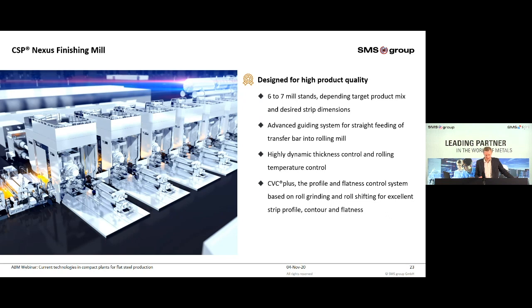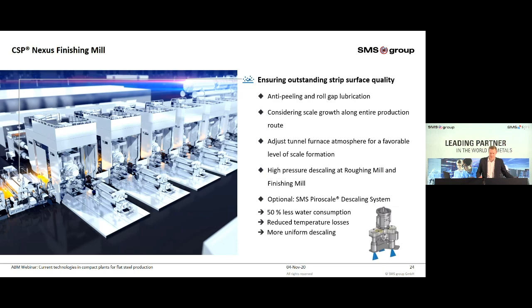The well-established CVC Plus system cares for excellent strip profile, contour, and flatness. An outstanding strip surface quality is guaranteed by roll gap lubrication and roll gap conditioning, including anti-peeling. The scale growth is considered along the entire plant. The tunnel furnace atmosphere is adjusted to a favorable level of scale formation.